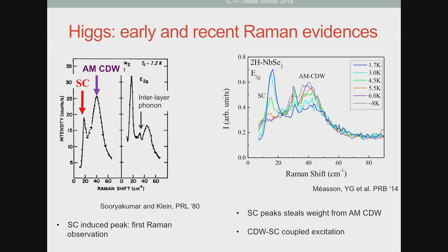And what you see is that, essentially, when you cool down below TC, it looks as if this mode here at low energy, the superconducting-induced mode, is stealing spectral weight from the amplitude mode of the charge density wave phase. So there seems to be an intimate link between these two excitations. And this was actually first seen as a function of magnetic field. So the same thing happens as a function of magnetic field.